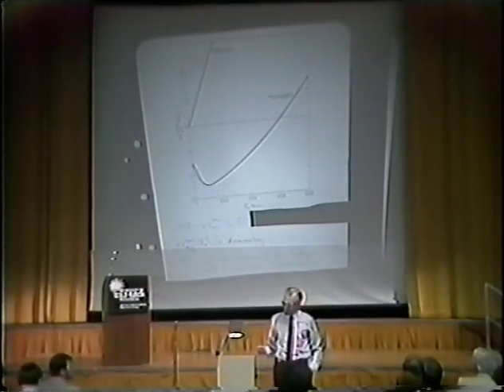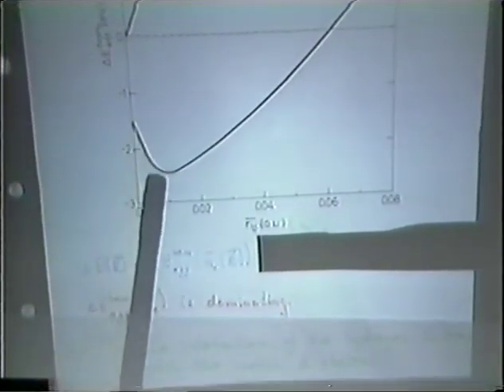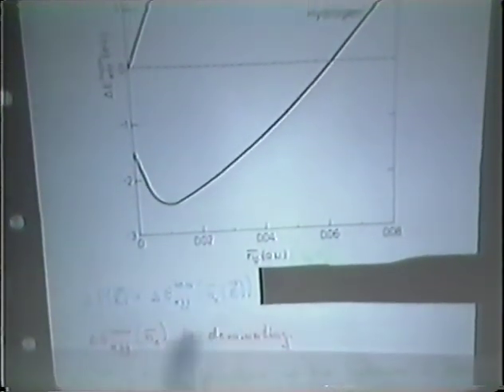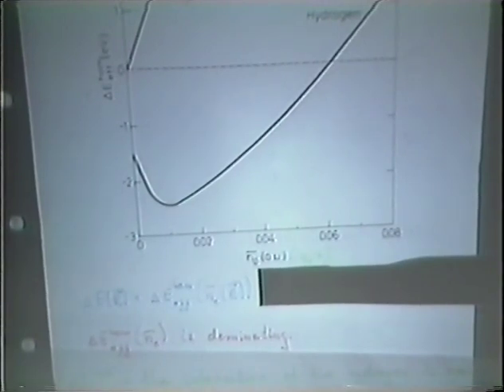If you look at the first term, which only depends on the interstitial electron density, that can be calculated once and for all for a given impurity. And of course, in this context, we are mainly interested in hydrogen. The curve is shown here, the embedding energy as a function of average interstitial electron density in atomic units. And you can think of this curve in a fairly simple way.